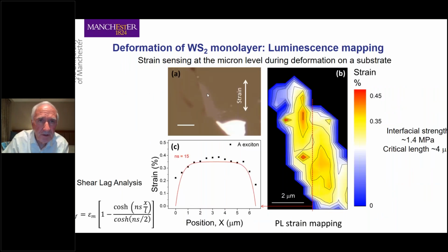And here's an example of just a single flake. Again, I'll talk about a single flake. This is a single flake about 2 microns long. And if you map the luminescence over the flake, here's the flake here, and you stretch it in the vertical direction, you get a yellow coloration in the middle of the flake and blue at the edges. So you have a high strain in the middle of the flake and low strain on the